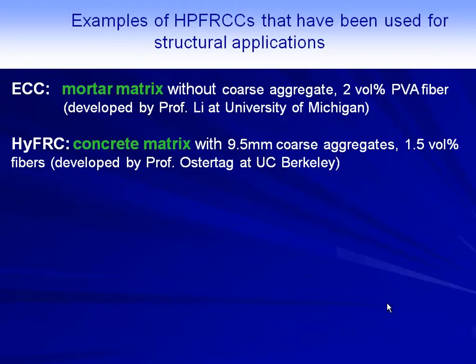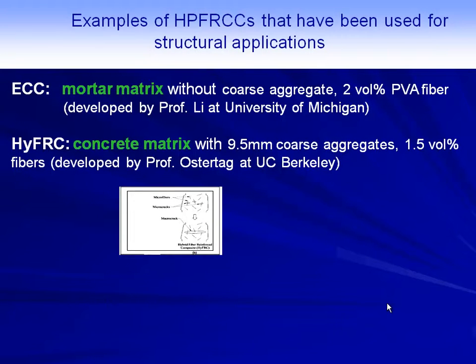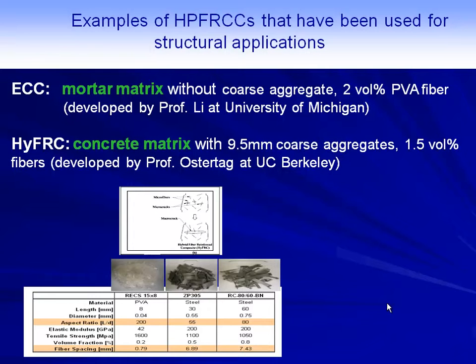So what you have in this case is, sorry, it's a little bit small, but you have here microfibers, and these microfibers bridge the microcracks right at the onset. They delay the propagation of these microcracks into macrocracks. Once you have a macrocrack, then the larger fibers will take over. So what you have here are the 3 different types of fibers that we're using in this hybrid fiber reinforced composite. We use the microfibers, PVA fibers, a very small percentage, right here 0.2%, and the rest are steel fibers with different aspect ratios and different strengths. Different lengths, different aspect ratios.